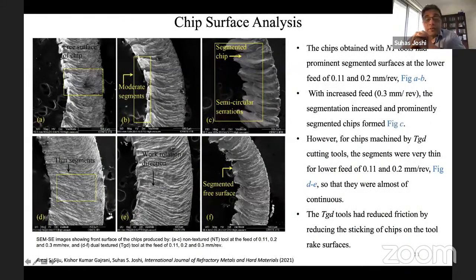The first effect in the machining process, which you will find, is on the chips which are produced. So these are the cross sections of the chips which are generated. You will find that the non-textured tools have significantly high strains. These lines indicate that it's an extremely strained material. And the more the strain, the more the energy required, the more the friction, the more the tool wear, and everything is high. Similarly, when you take it at little higher feeds, the rate of machining is higher. At that point, you find that the segments are very thick and prominent, and those segments will cause a lot of chatter in the machining process, which can damage the surface finish significantly.